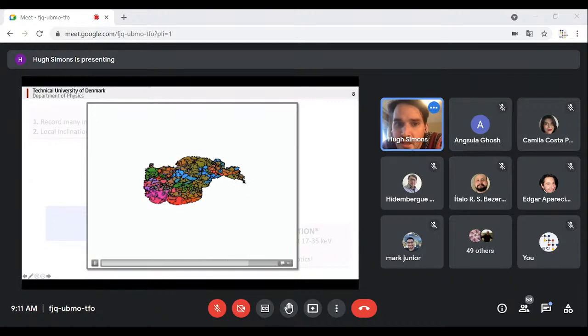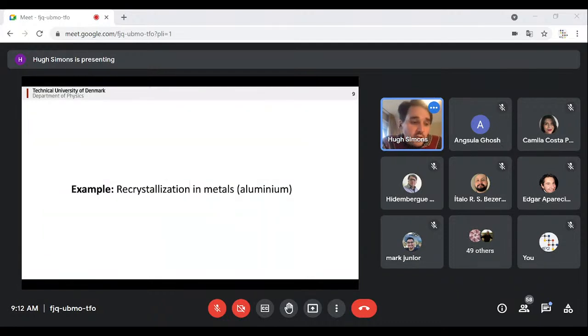So this is essentially a grain of aluminium where the subgrains are given by different colors. So you can see we have some orientation variation inside our grain, and we slowly build up this picture as we scan through orientation space effectively. So that's pretty much how the technique works.